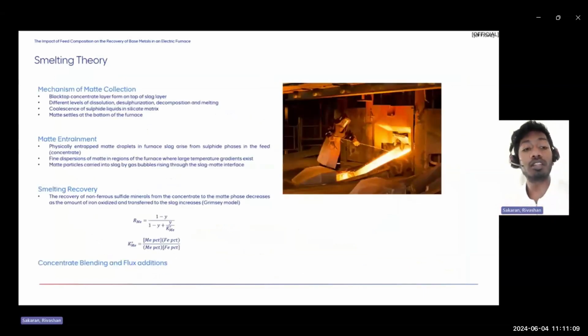So how does this occur in the smelter? Well, the black top layer occurs when the concentrate is fed to the top of the slag layer, where it goes through different stages of dissolution, desulfurization, decomposition, and melting. As a result, these then form in, or coalesce within, the silicate matrix of the slag, and subsequently settle through density differences and coalesce and settle at the bottom of the furnace. There are some physical entrainment issues, where there may be physically entrained matte droplets still in the furnace slag. This can occur where there are large temperature gradients within the furnaces, or when the gas bubbles forming with the reactions in the furnace lift the matte particles up to the higher levels in the slag.